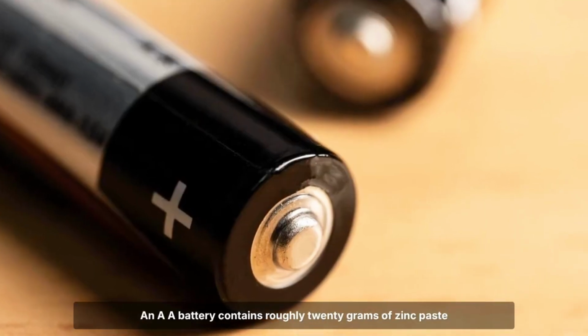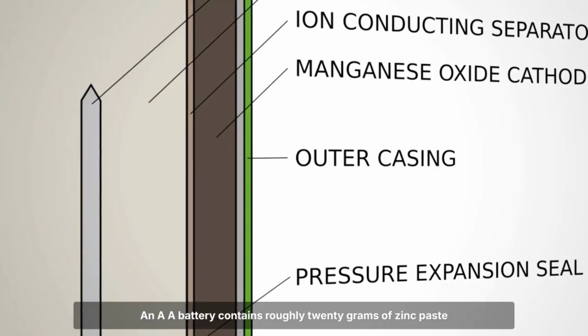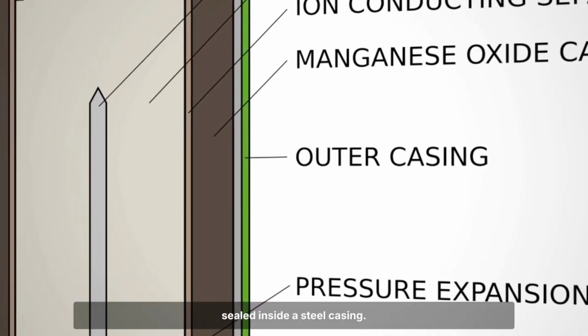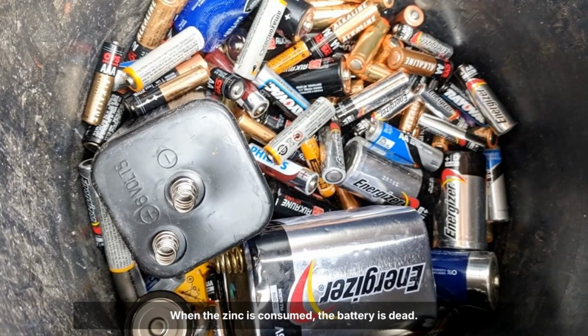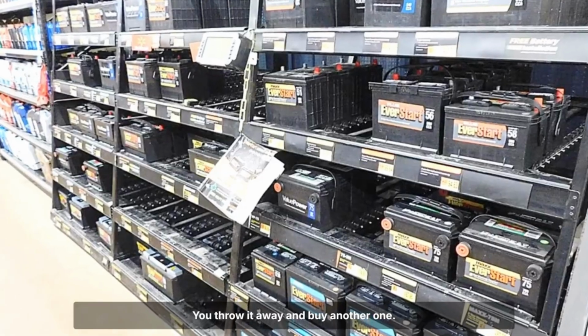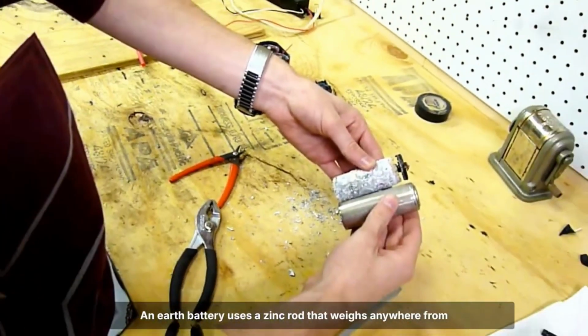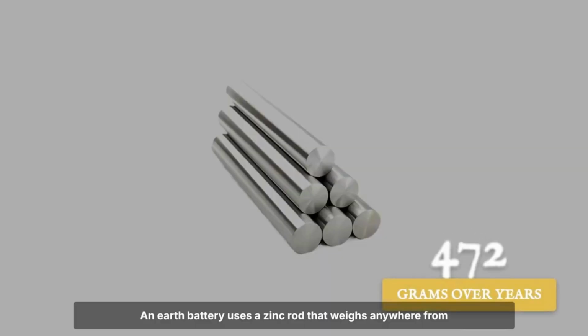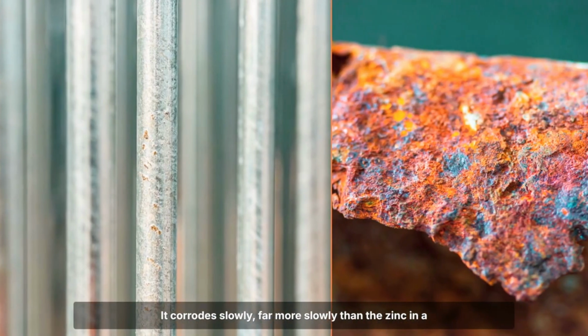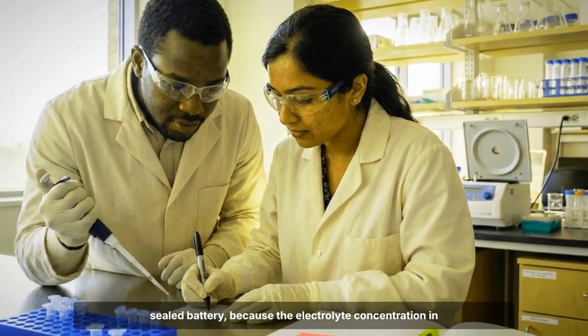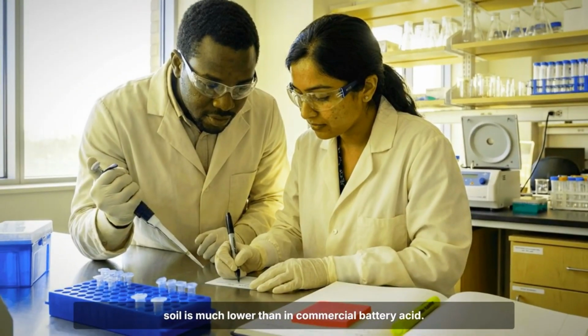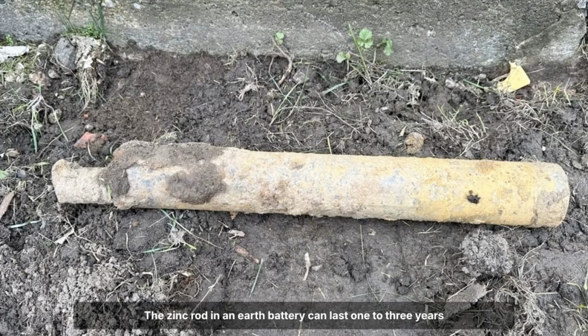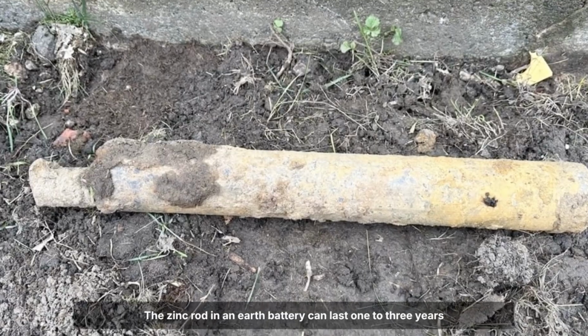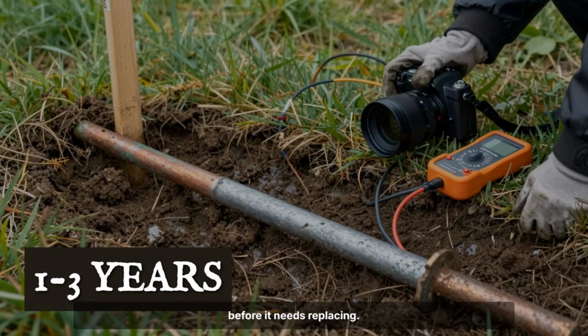An AA battery contains roughly 20 grams of zinc paste sealed inside a steel casing. When the zinc is consumed, the battery is dead. You throw it away and buy another one. An Earth battery uses a zinc rod that weighs anywhere from 100 to 500 grams. It corrodes slowly, far more slowly than the zinc in a sealed battery, because the electrolyte concentration in soil is much lower than in commercial battery acid. The zinc rod in an Earth battery can last 1 to 3 years before it needs replacing.